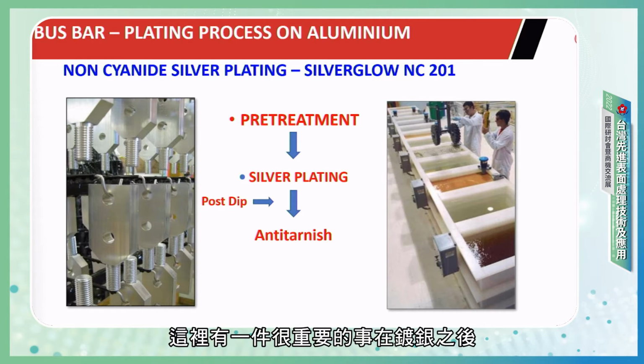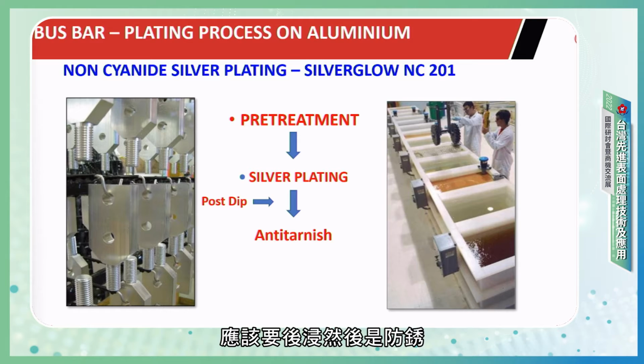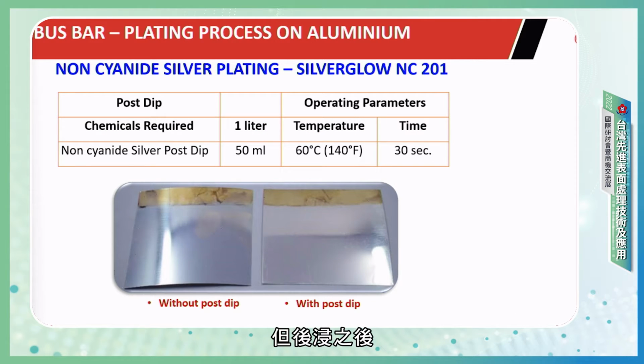But here one thing is important: after silver plating, one should apply the post dip followed by the antitarnish treatment. This post dip makes the component brighter. Before post dip, the situation is not that lucrative. You can see that without post dip, the component or the panel looks bluish in appearance, but with the post dip, we get a brighter appearance.